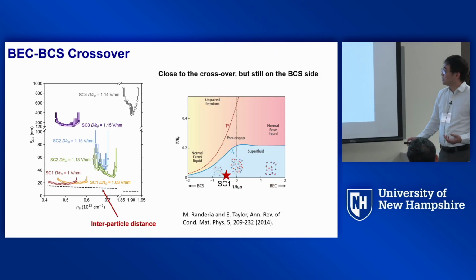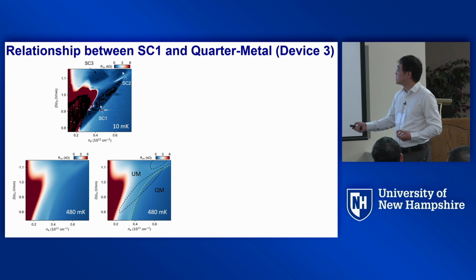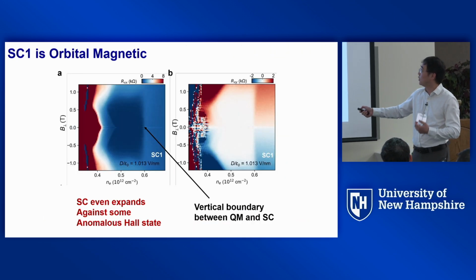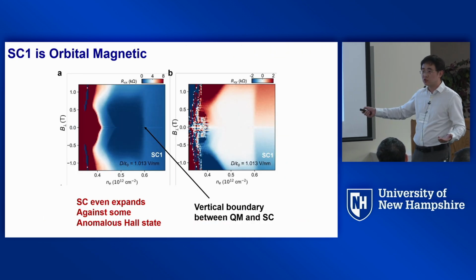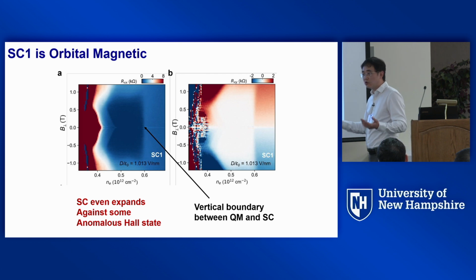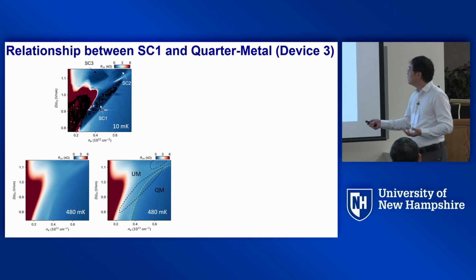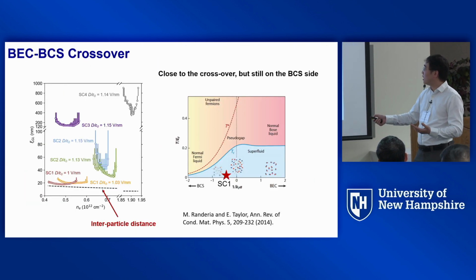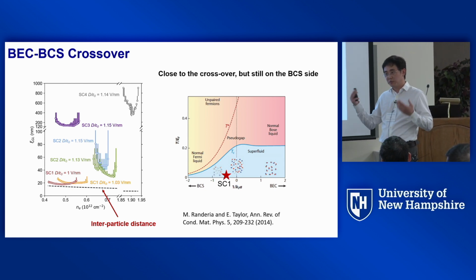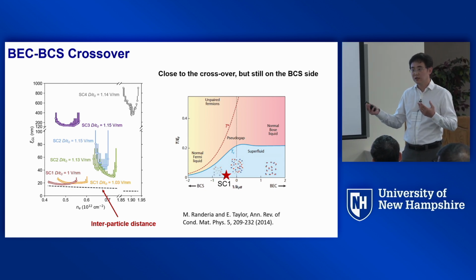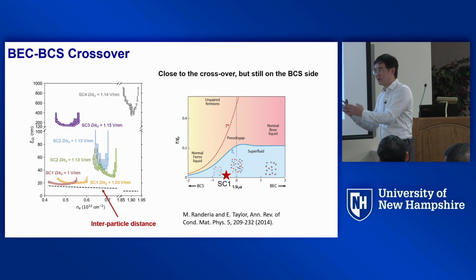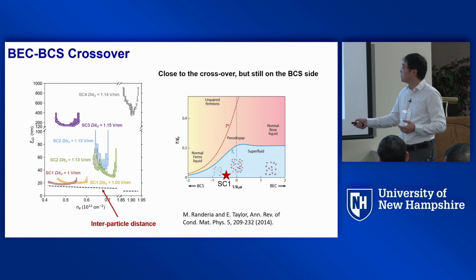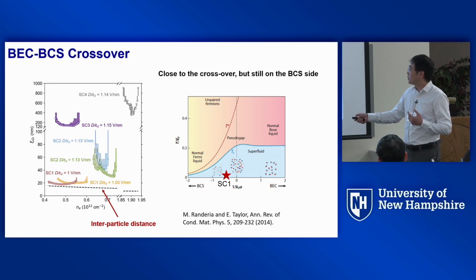Okay? And another thing I want to bring to your attention is that when you see this out-of-plane magnetic field dependence, you probably have noticed that, wait a second, it's a very weak superconductor. It's only 200 millikelvin. But it can persist to out-of-plane magnetic field almost 1 Tesla. This is totally unusual. So the thing you can do is, based on that out-of-plane critical field, you can just use BCS to estimate what is the coherence length. Of course, that may not be appropriate because this is most likely not BCS. But if you do that, you'll get a coherence length on the order of 20 nanometer for SC1.